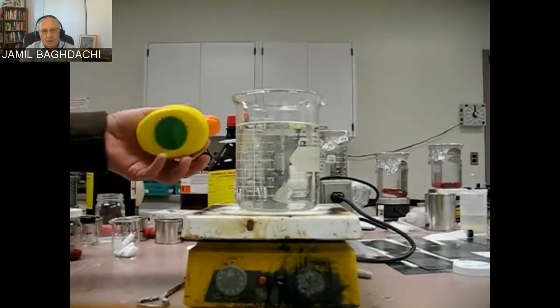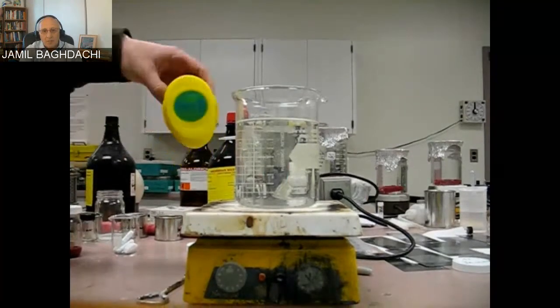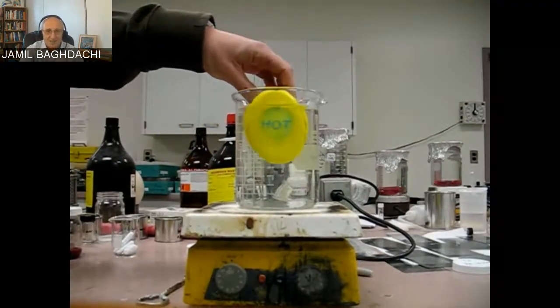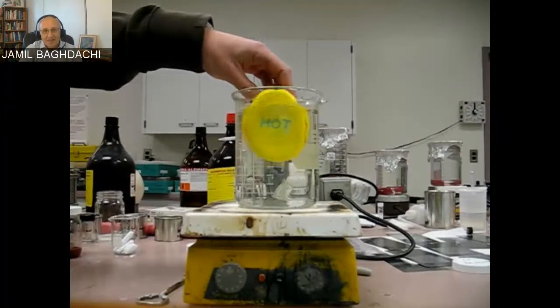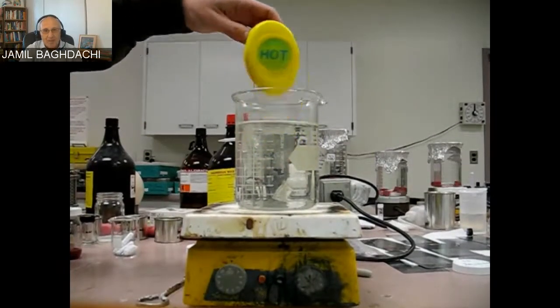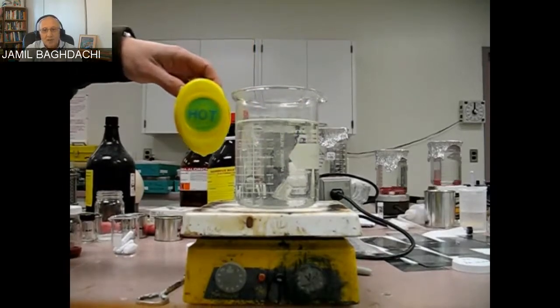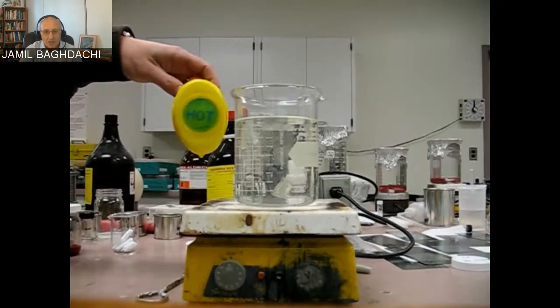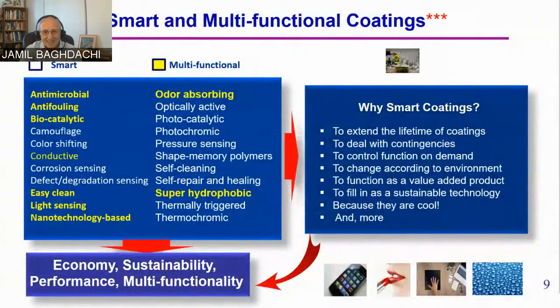There we go. That ducky, it's sold in Bed Bath and Beyond, at least then, for $2.50. I got about a cent off of that each. Not anymore. As you can see, as a function of temperature, at 42 Celsius, above that temperature it gradually begins changing color. It indicates that one would not put the baby in a hot bath. This is to show that it can be made.